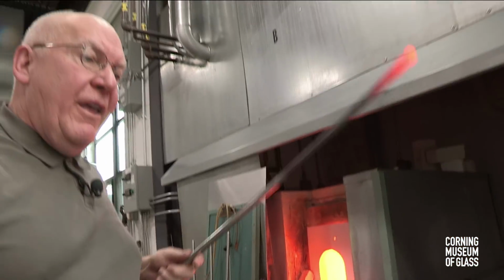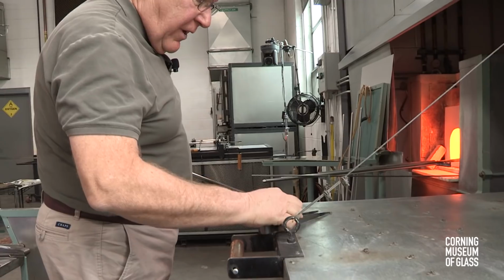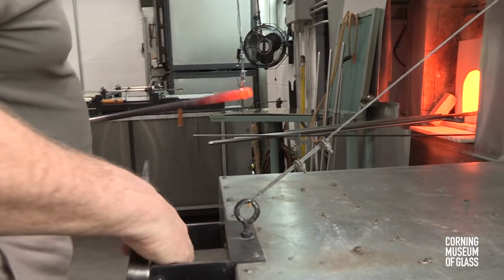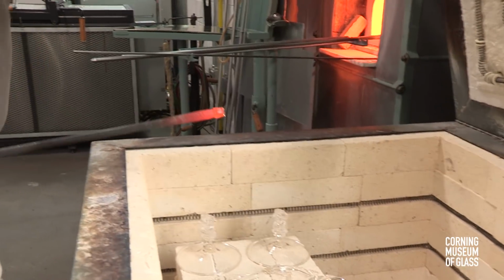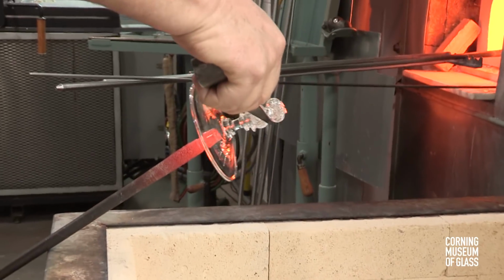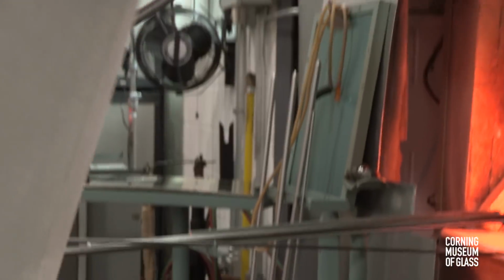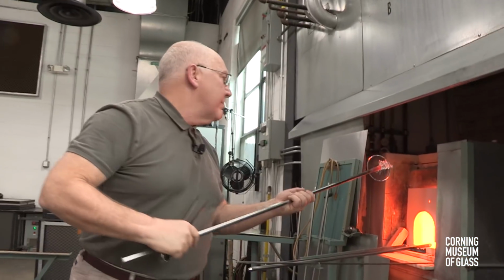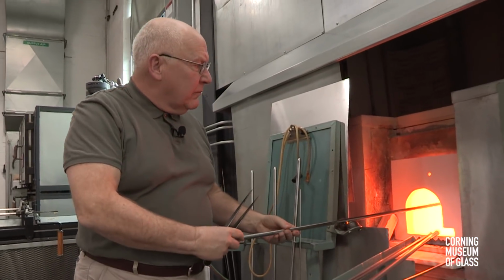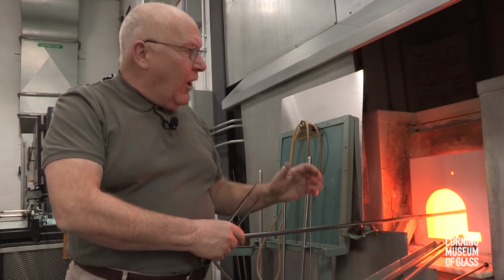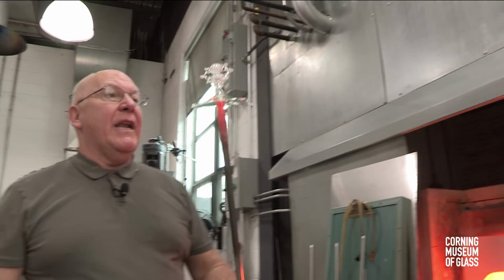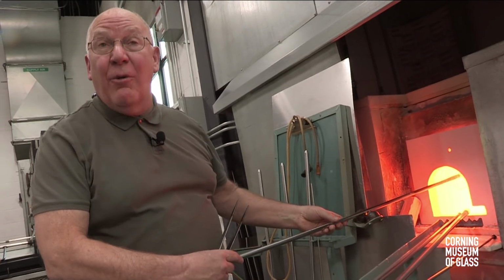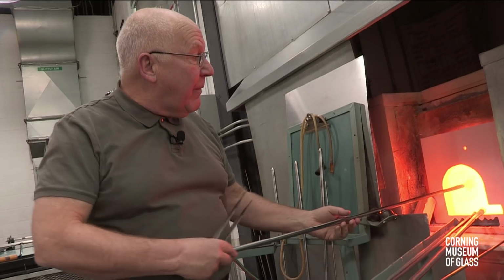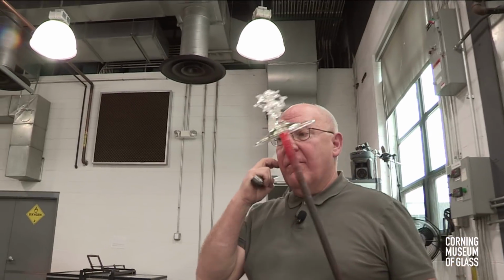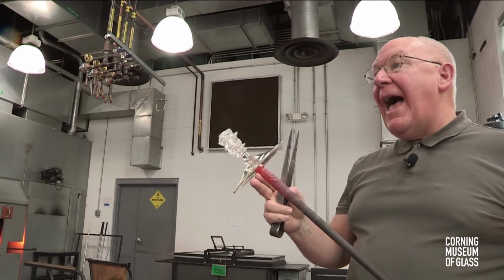And here we go. This will be the foot. I'm going to marver it, flatten the end, and put the foot on. The pickup box is holding at about 950 Fahrenheit, and for this glass and that controller and that thermocouple, 950 is the magic number at which the parts, if left in there for hours, won't slump.